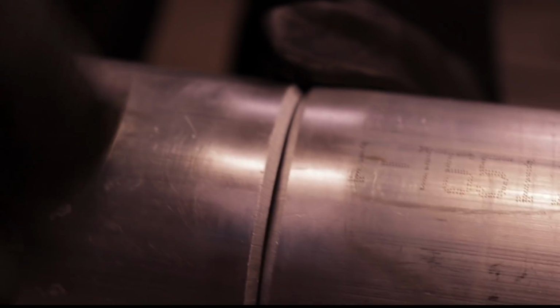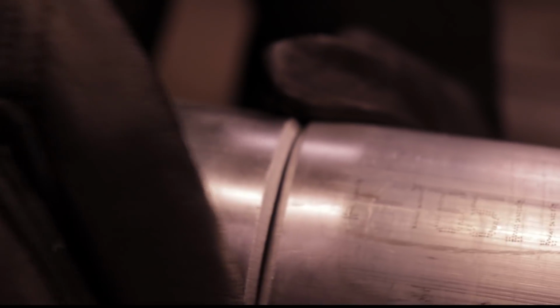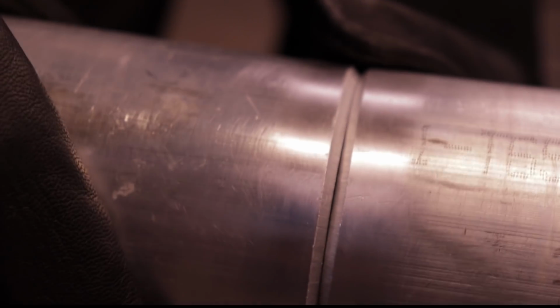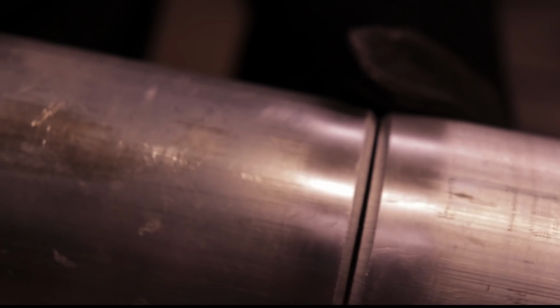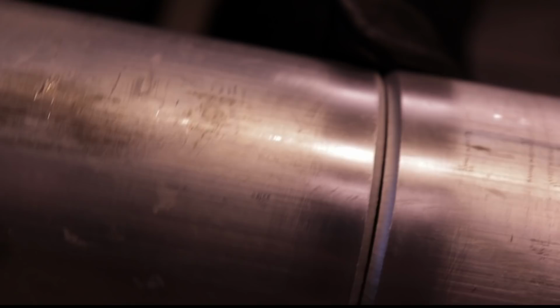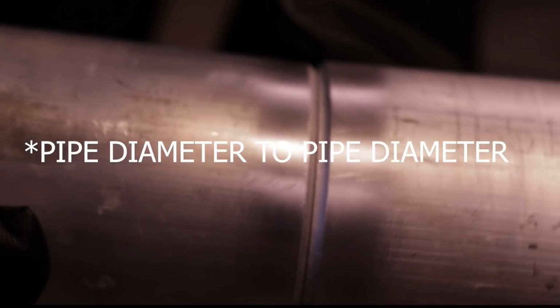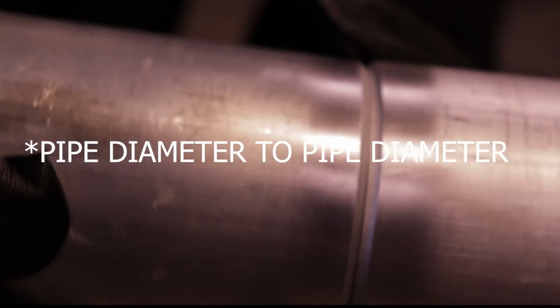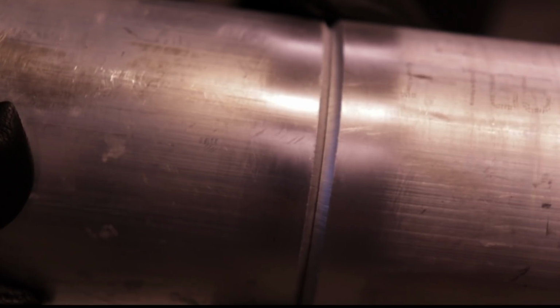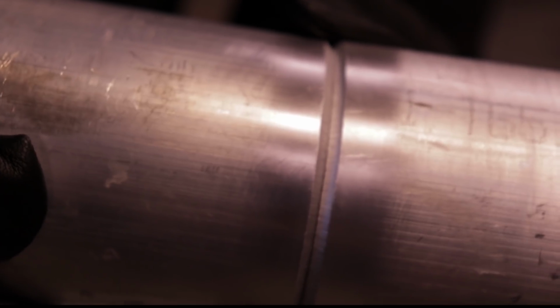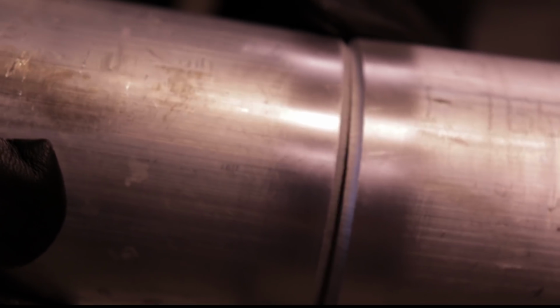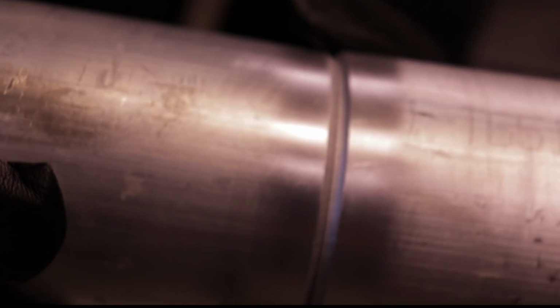The difference between tubing and pipe: tubing is measured on the outside diameter, and pipe is kind of the inside diameter. And then they have different schedules, so Schedule 40 varies from pipe size to pipe size. I think 3-inch Schedule 40 is 1/4 inch thick, and then Schedule 80 is almost double that. It's not quite 1/2 inch, it's probably 3/8. It's really weird how they go about it.